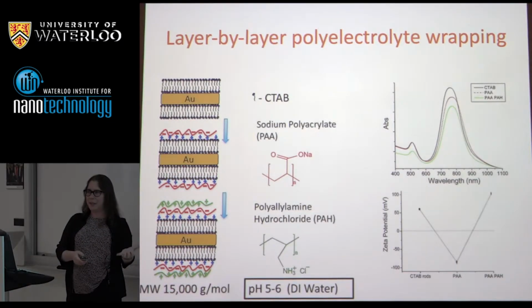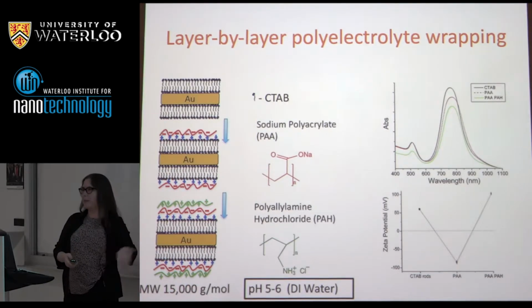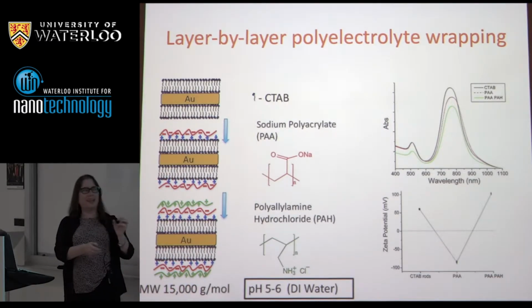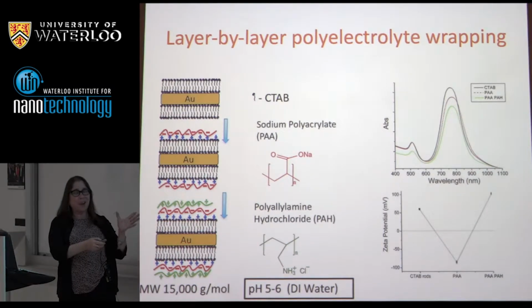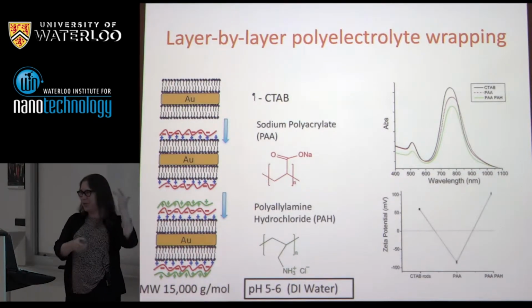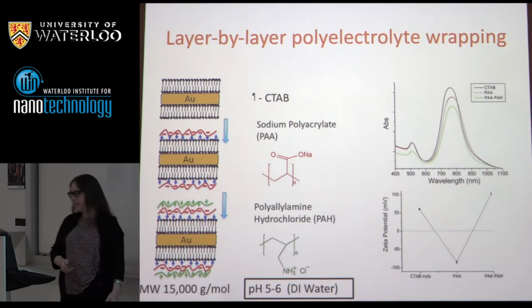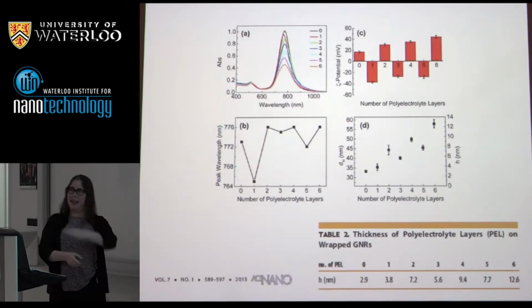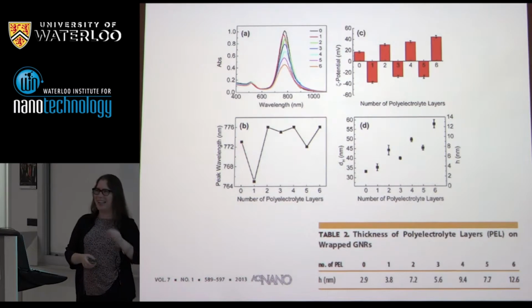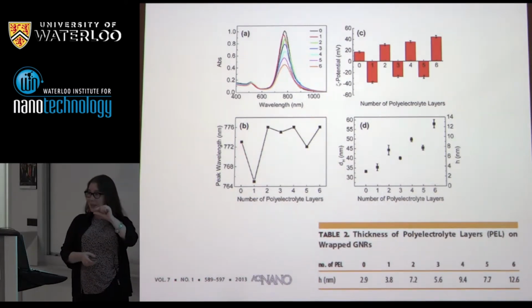And on a flat surface, like a microscope slide, you could do this 100 times. Back and forth, back and forth. On a colloidal particle where you've got to separate free polymer from the particle, you can maybe get about 10 layers before you start losing too much sample. So how thick are these layers? On a flat surface, by ellipsometry, those particular polymers I just showed you are about 1.5 nanometers each. So that's pretty nice and tight.